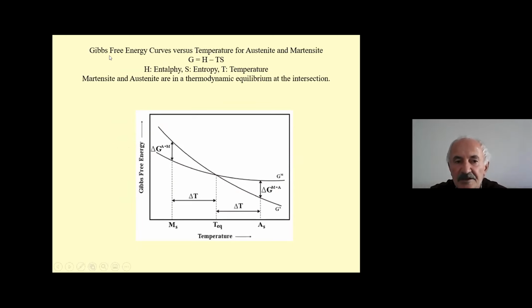This is the Gibbs free energy curves versus temperature for austenite and martensite. On cooling, martensitic transformation occurs and follows this path. This is the equilibrium temperature, and martensitic and reverse austenitic transformations don't occur at the same temperatures, and a driving force is necessary due to the solid state phase transformation.